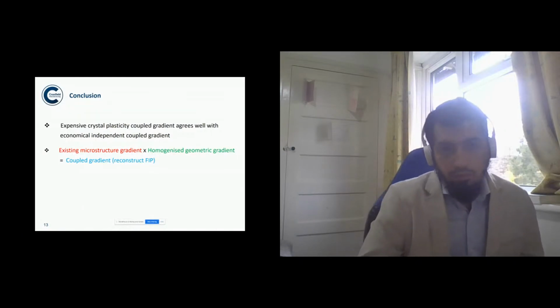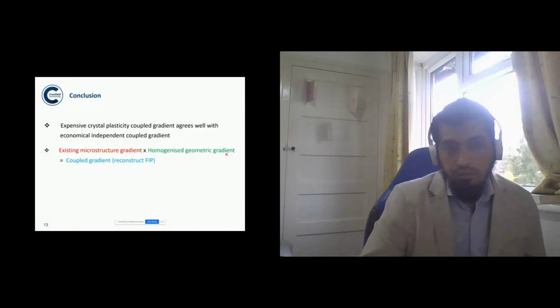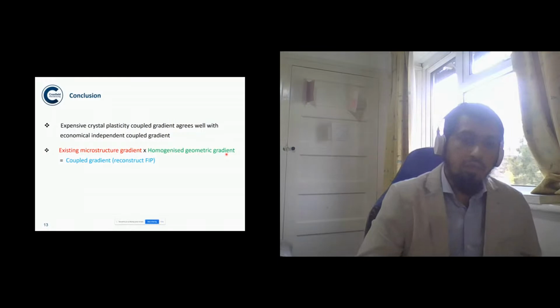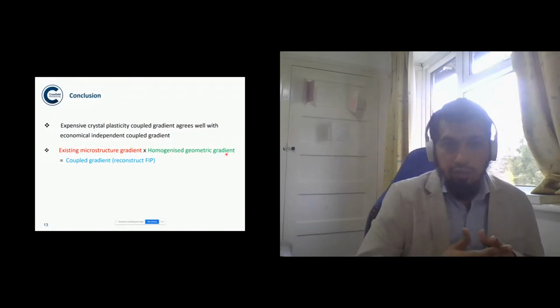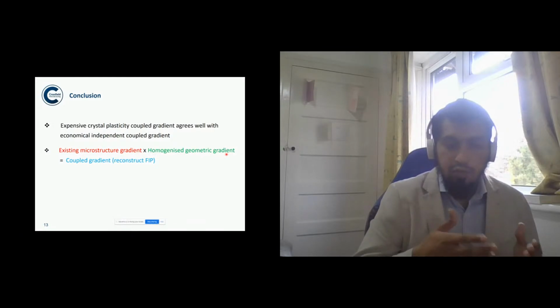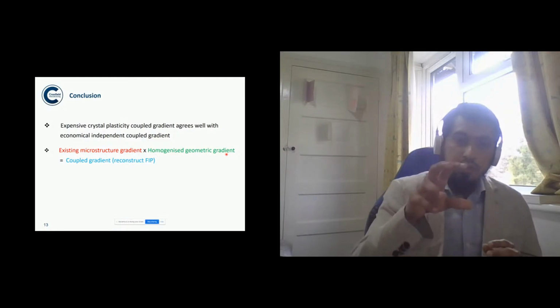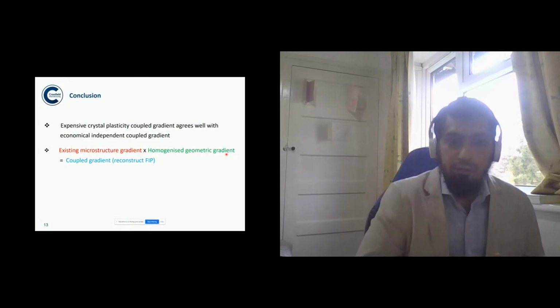Gustavo asked, how do you extend this to life quantification? Okay. So this is only the driving force, the effect of the gradient. So we need to couple it with, for example, the life equation. In the life equation, we have the driving force as a function of crack length, and that has a direct relation with the life. So we can directly use this coupled gradient there, and we can predict the life.